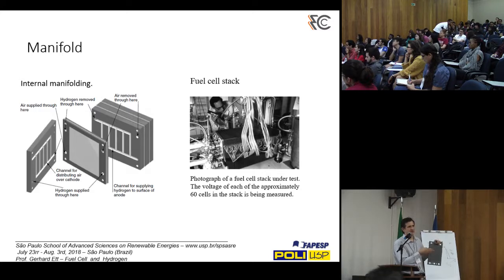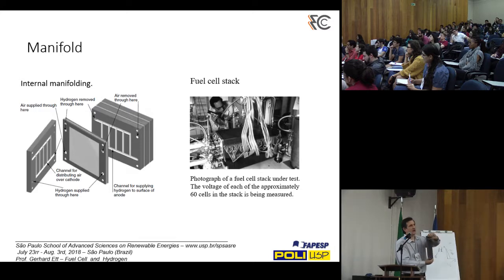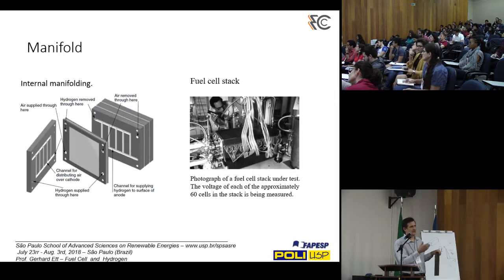Sometimes if you increase the current density of the cell, you need more water. If you use a current density lower than 0.3 ampere per square centimeter, you don't need extra humidification. But if you go above 0.3 ampere per square centimeter, you need extra humidification. You can have extra humidification on the anode and also at the cathode, because we saw here that the membrane, the Nafion that we use, needs water. If you don't use water, we don't have the diffusion through the membrane. Okay.